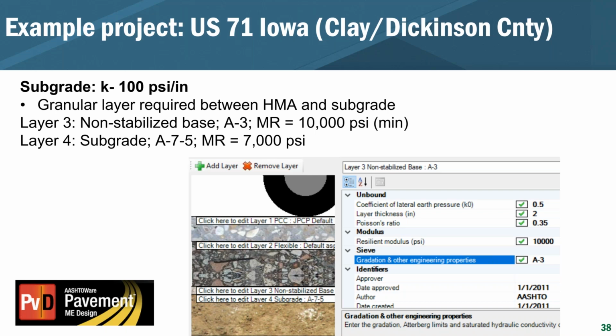And then for the subgrade, I got back to around where we should be, A-7-5, and then assigned a resilient modulus of 7,000. Now, again, I'm doing this with the intent of trying to make that K value as close to 100 PSI per inch as possible, because if you remember when we talked about how Pavement ME designs, it's going to couple that concrete layer and the asphalt layer together, make that an equivalent slab. And then all layers beneath it, it's going to create an equivalent stiffness or a K value based on the resilient moduli. So I want to try to play with these layer stiffnesses to see if I can get an approximate 100 PSI per inch K value.